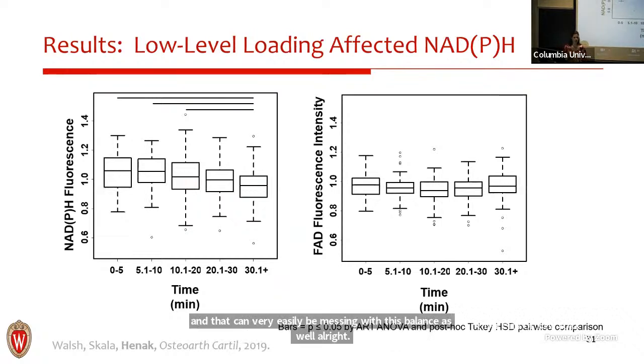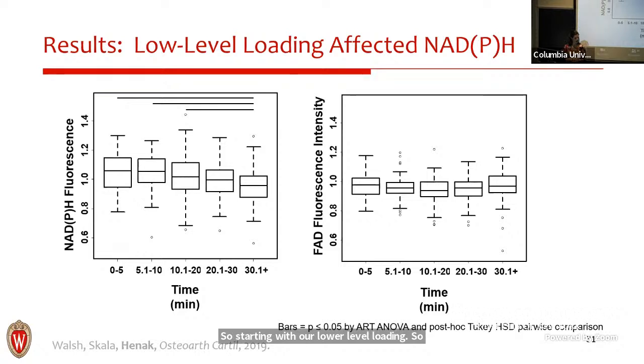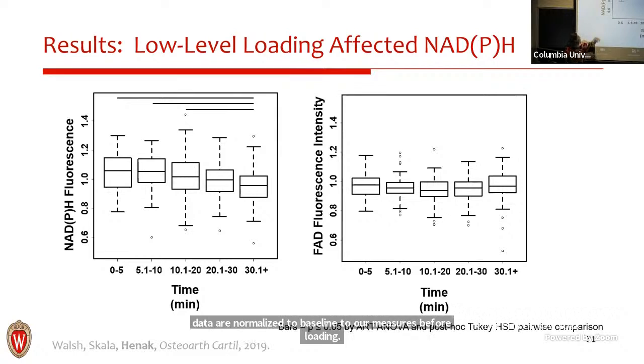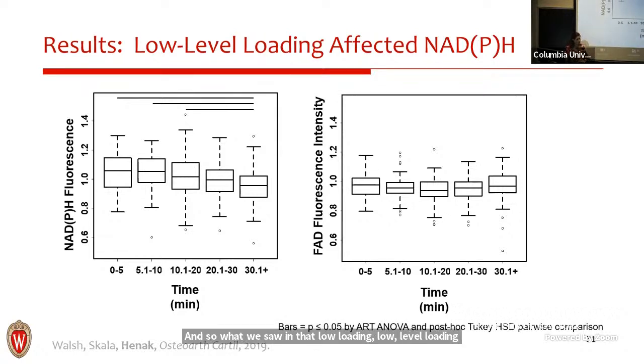All right, so starting with our low level loading. So this is that compression across the whole sample surface. Here we have our NADPH channel on the left, our FAD channel on the right, and these are binned by time, right? So we applied our loading, and then we looked at different time bins after loading to see these responses. All of these data are normalized to baseline, to our measures before loading. And so what we saw in that low level loading was that our NADPH signal goes above 1 immediately after loading, but it comes back down to about 1 over those long time periods. But we didn't see any change, any response in the FAD channel.